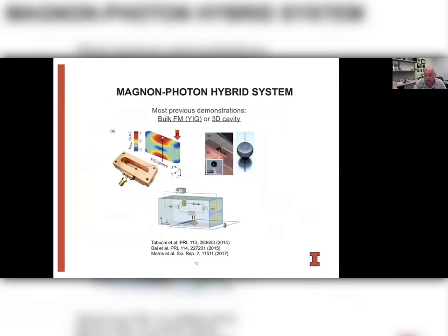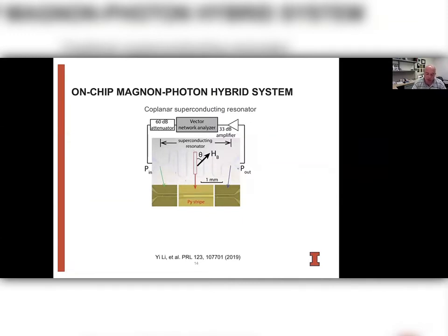So most of the previous investigation of hybrid magnon-photon systems was based on bulk ferromagnetic materials, where you had a bulk sphere of YIG that was then placed in a big three-dimensional cavity for microwave photons. And these were used for demonstrating strong magnon-photon coupling. Now, in contrast, what we wanted to do is use a planar superconducting resonator and integrate a magnetic structure in here. And here you see an optical picture that shows our permalloy stripe integrated on top of the signal line of our superconducting resonator, which is capacitively coupled at the end to further coplanar waveguides.